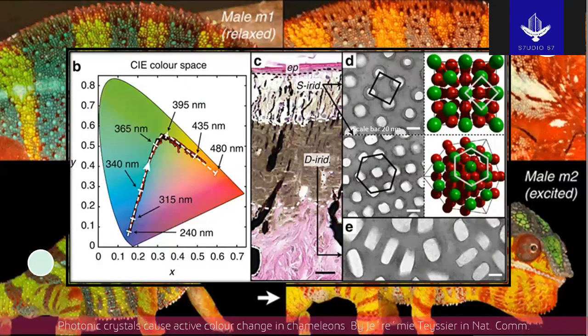The arrangement of high and low refractive index materials — the cytoplasm at 1.23 and the guanine crystal at 1.83 — makes them behave as a photonic crystal. When a male panther chameleon is in an excited state, the inter-crystal distance changes and the morphology changes from a square to a hexagonal distribution arrangement of guanine crystals, which shifts the diffracting wavelength and causes the observed color change.